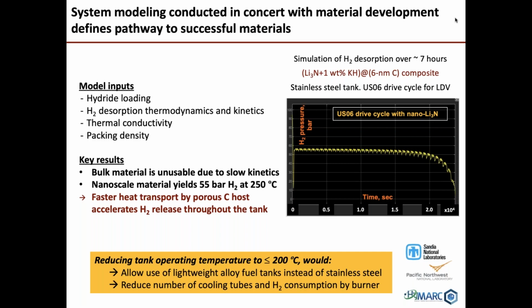We provide the loading there. We provide the thermodynamics and kinetics of that material, its thermal conductivity, and the packing density. And what we find is if you take that information for the bulk material and put it into the framework model, you can't even start the fuel cell. And the reason for that is that the heat that is required to drive the hydrogen off, there's too much of it needed. You can't heat the bed up uniformly and generate enough hydrogen at the rate needed to run the fuel cell. So the thing just doesn't even start.